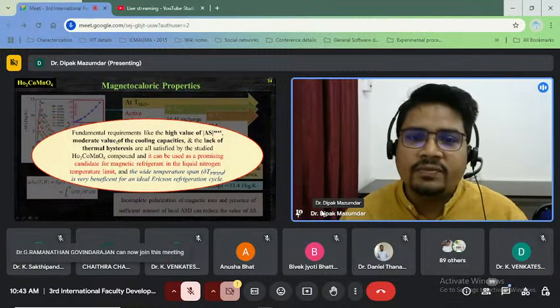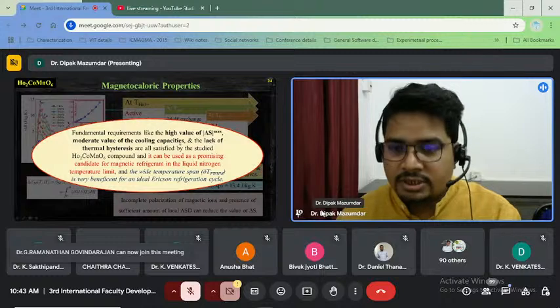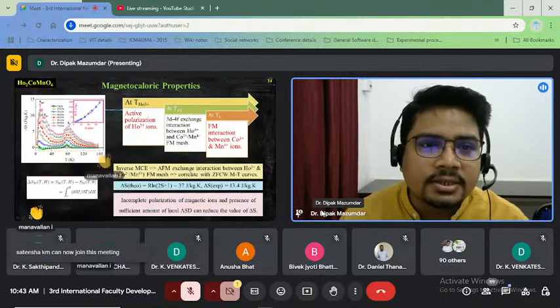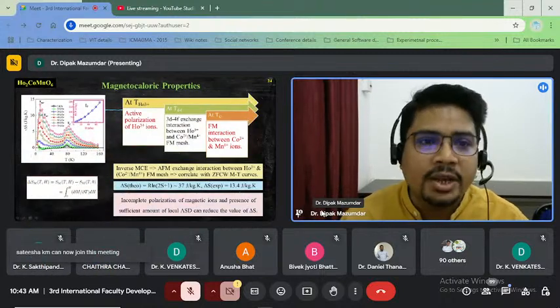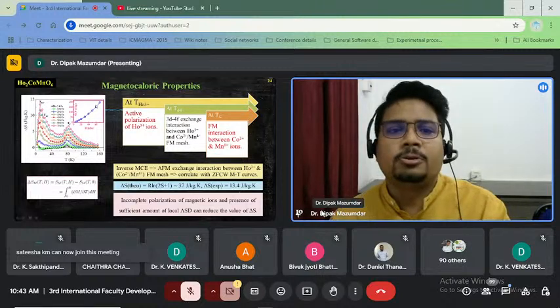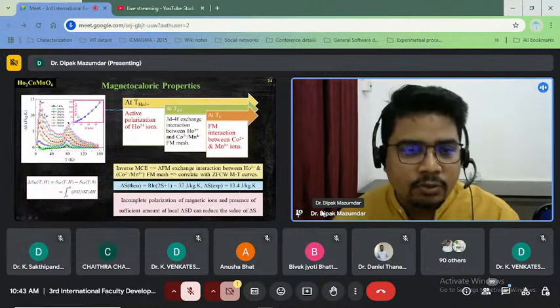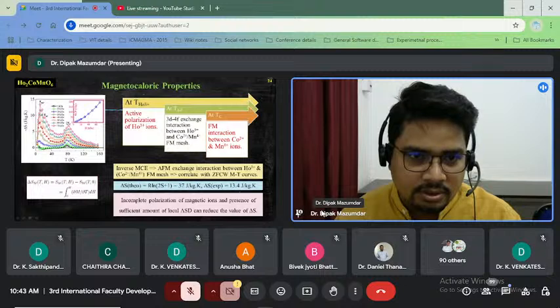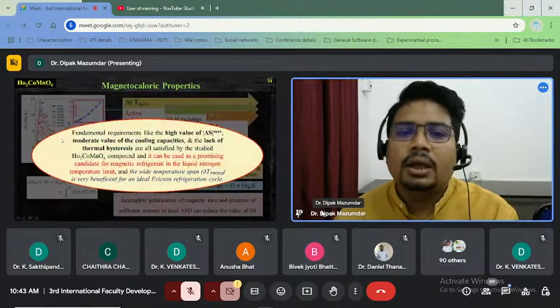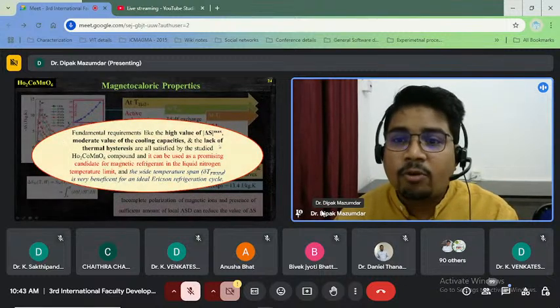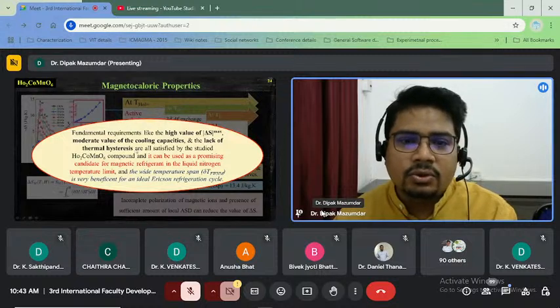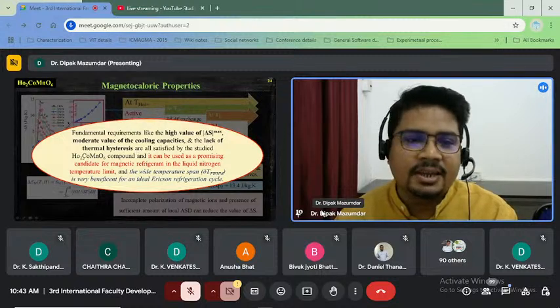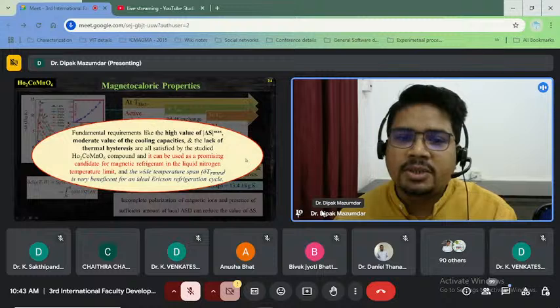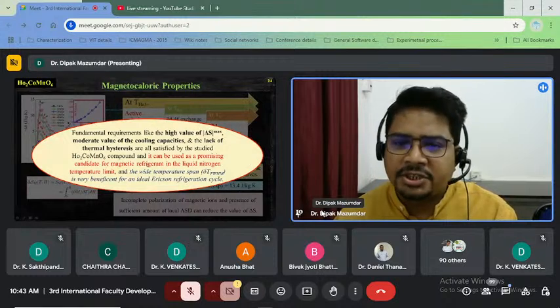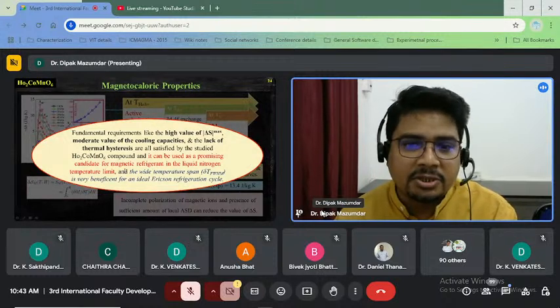Then also moderate value of cooling capacities, which I calculated in this graph, is approximately around 280 joule per kg. So RCP we can calculate it from this region. And we can see the lack of thermal hysteresis in the graph. So they are all satisfied by the studied Ho2CoMnO4 compound, and it can be used as a promising candidate for magnetic refrigeration in the liquid nitrogen temperature limit.